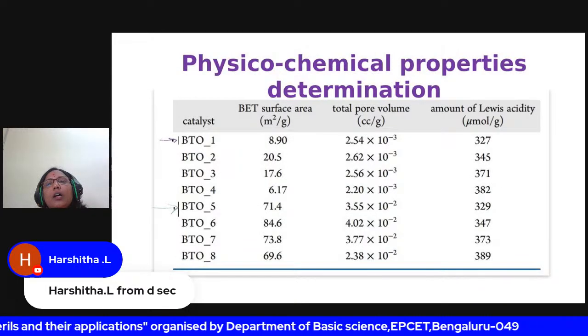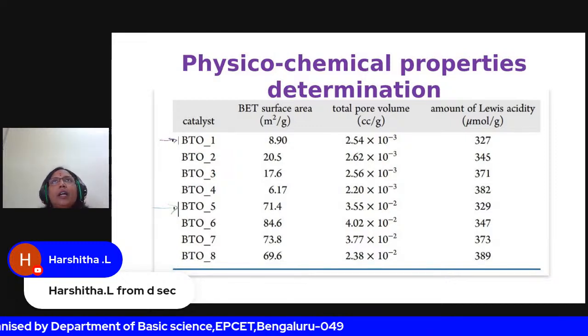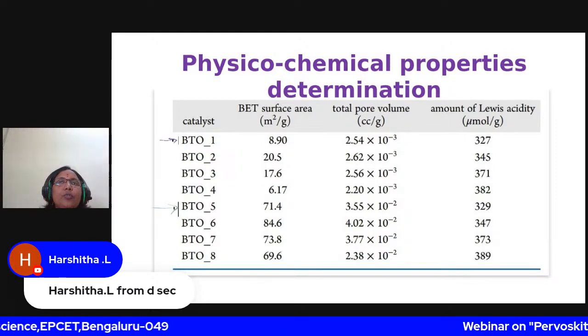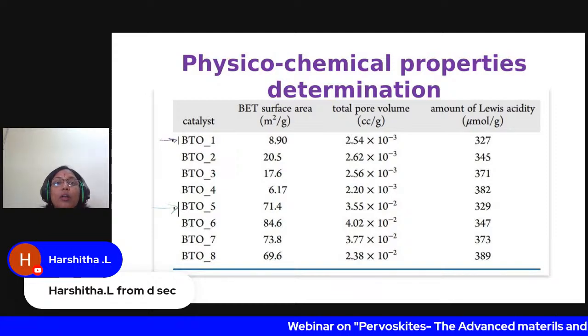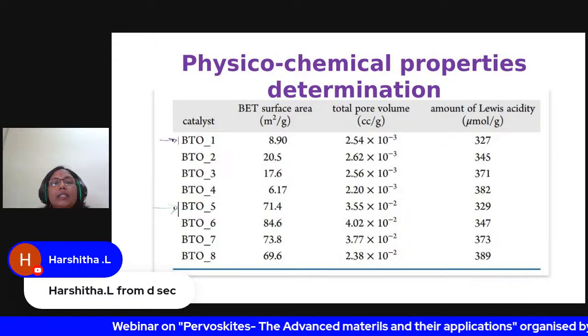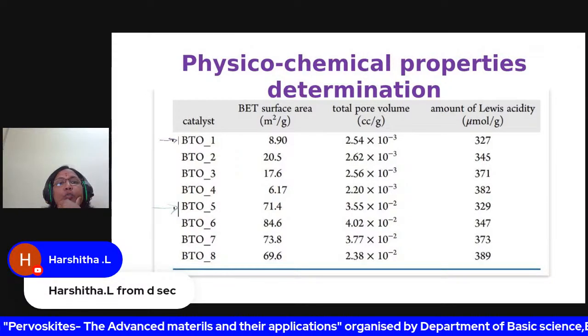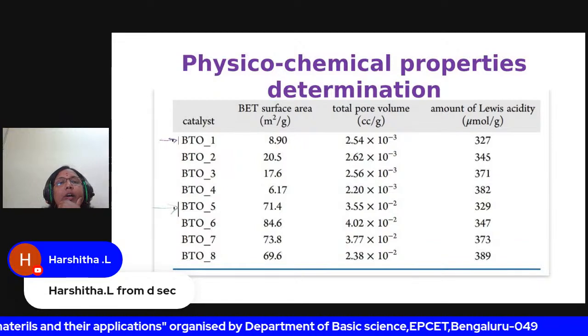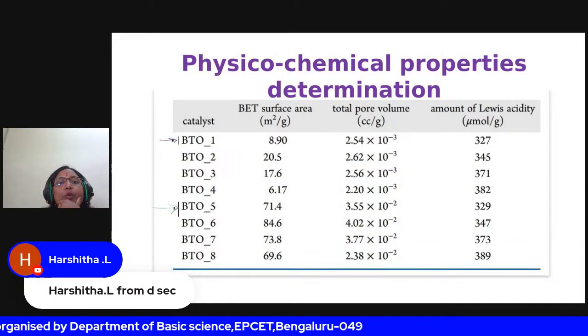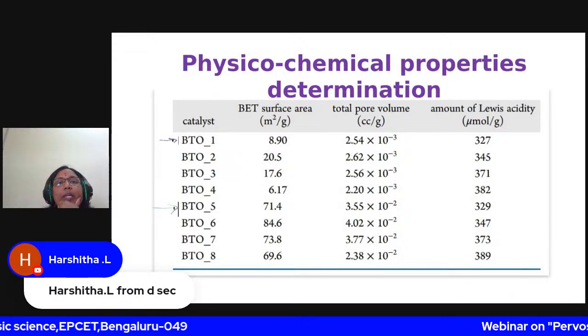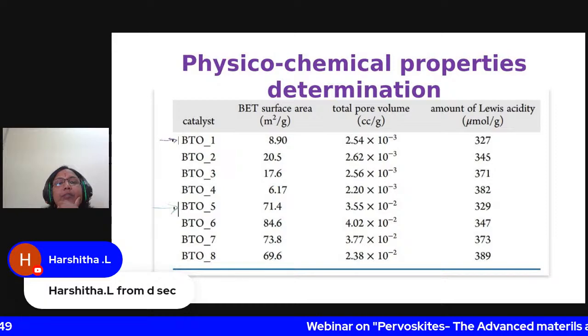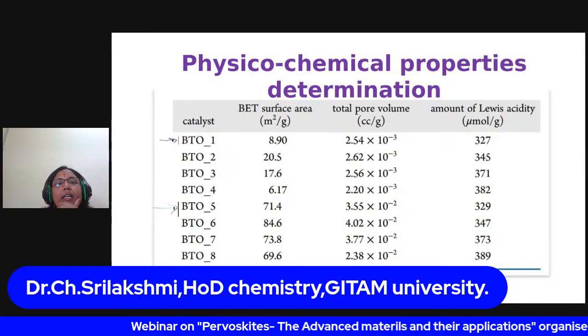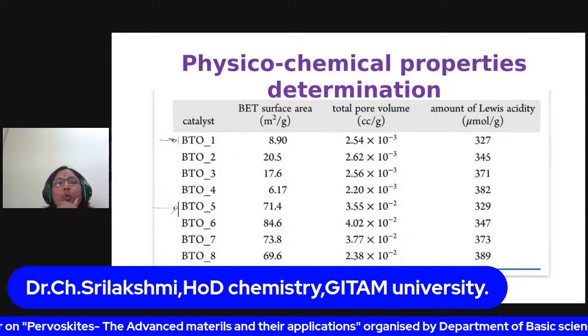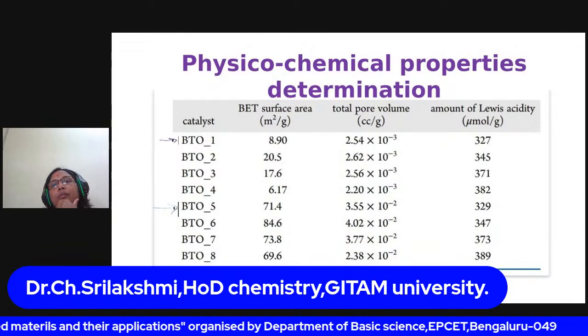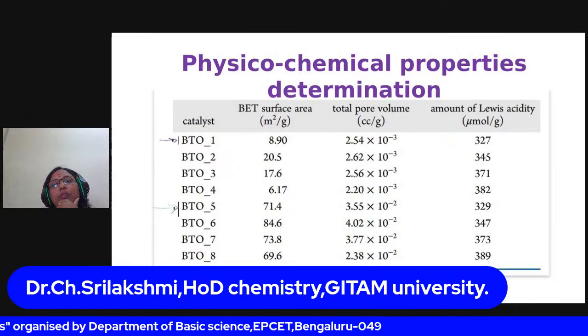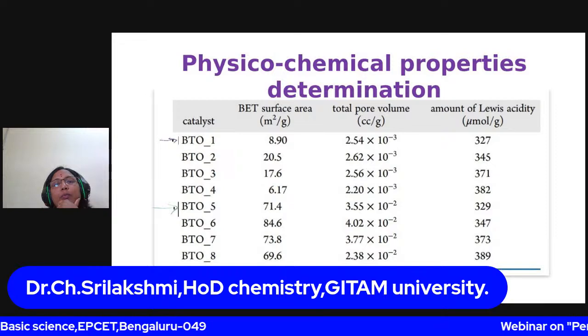So what are the other physicochemical properties we can determine? BET surface area. TEM analysis gives an idea that the particle size of microwave synthesized materials is small. So what do the BET surface area results show? You can see here, this is 1 to 4, this is barium titanate, and 0.5, 2.5 and 5% chromium doped, CO synthesized, which is the conventional oxide method. So the BET surface area of barium titanate synthesized by the CO method is 8.9, whereas you can see here the same barium titanate without chromium is 71.4. Almost 10 times, and for 2.5% chromium it is 20.5.